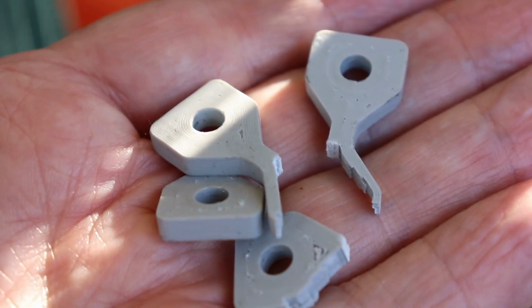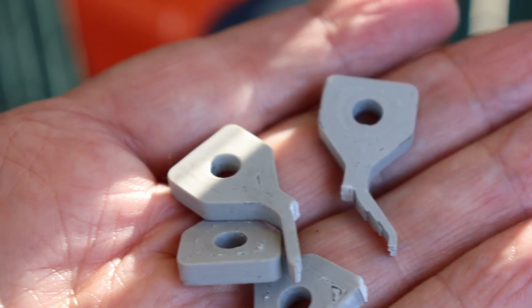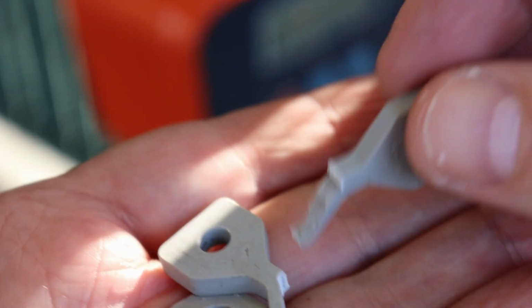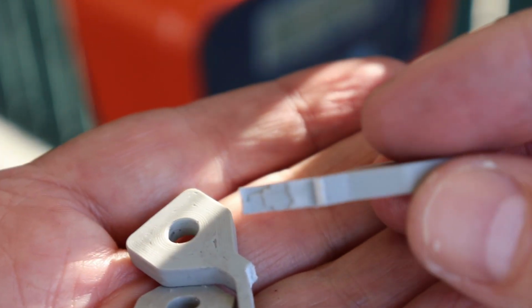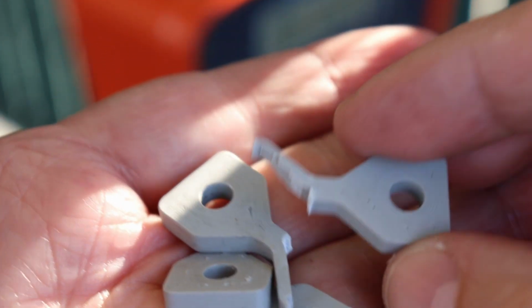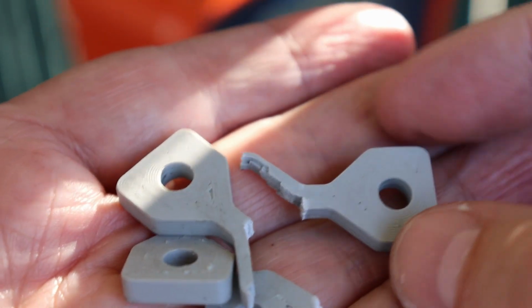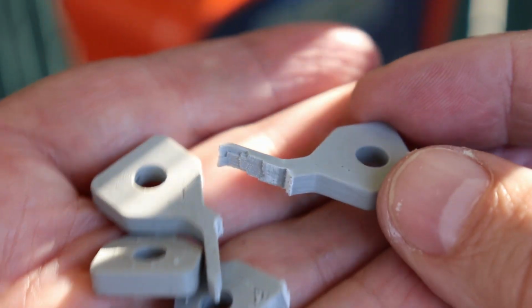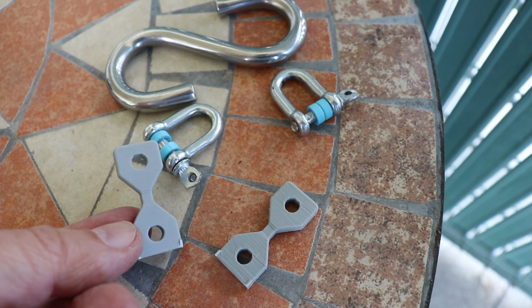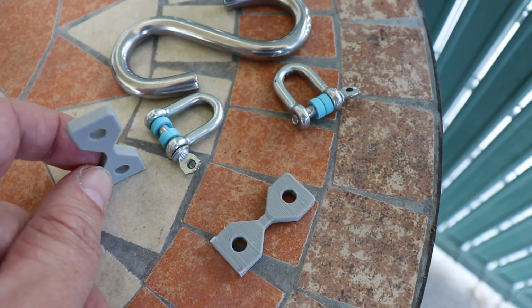As you can see, in both cases they didn't break on the smallest cross-section area, and this means that something is wrong with the layer adhesion. So I'm very curious about the next test. Layer adhesion test. So these test specimens are printed in vertical position.